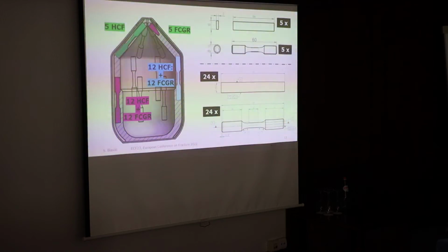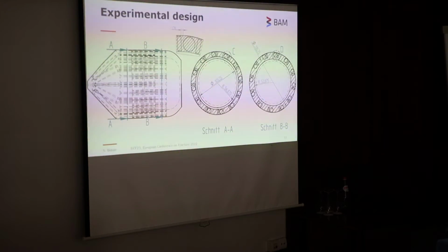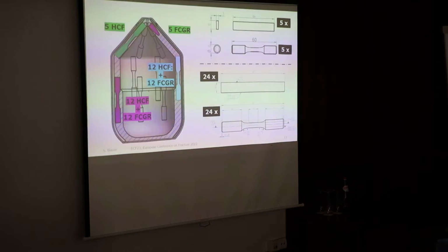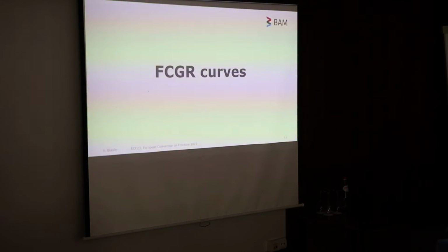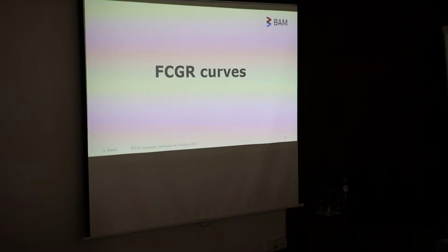We can see the round ones, which correspond to the high cycle fatigue specimens, and the rectangular ones, which are used to complete the fatigue crack propagation tests. According to this, for each vessel, we are collecting in total 58 specimens, so we have a lot of information to characterize. And I will show you the main results up to now. I should mention that up to now we don't have the whole results, just preliminary ones.